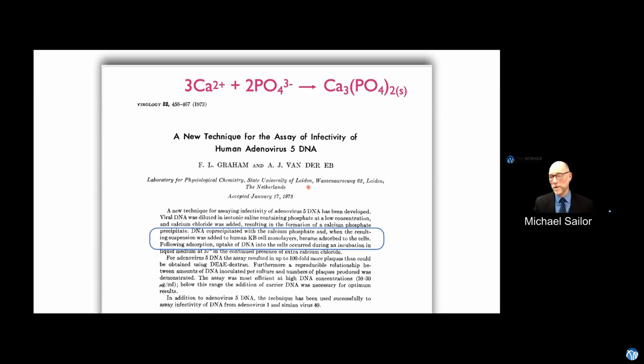And the trick that's now a very established, really a classic protocol, is you just squirt in a bunch of calcium and some phosphate. So calcium chloride, calcium ion, and phosphate will precipitate and make solid calcium phosphate, a very low solubility compound. Basically it precipitates a small nanoparticle. At this time they just called them particles, because back in 1973 it wasn't so popular to use the nano word. But they were making nanoparticles or micron-scale particles, some fairly large, basically a precipitate using this kind of calcium phosphate chemistry.